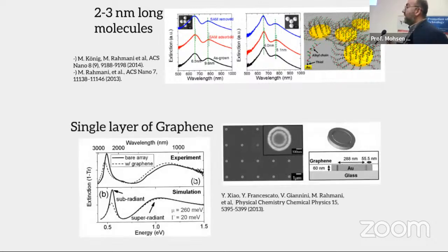And not even that, graphene. A single layer of graphene is only 3 to 4 angstrom, even less than 1 nanometer. But still optically we can detect that. Nevertheless, both of them are in the solid state, so the concentration of the substance we want to detect is high, so it's easier to detect. But when you go to the gas phase, it becomes very, very difficult because the concentration of those substances drops significantly. That's why these nanostructures cannot straightforwardly and easily be used to detect those biomarkers or substances in a gaseous atmosphere.